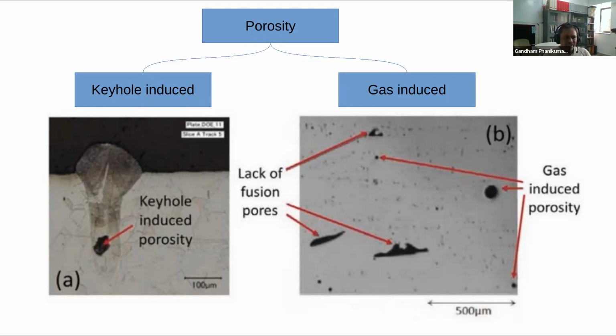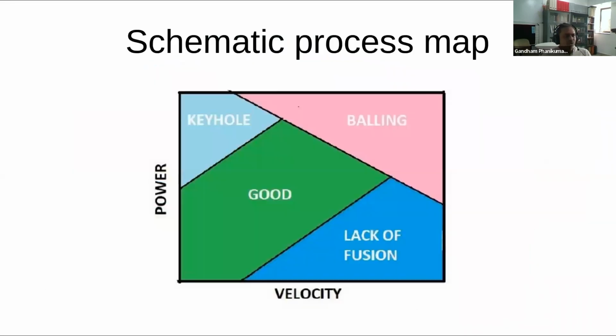The gas-induced porosity is difficult to eliminate using the powder characteristic, laser characteristics, because it is actually coming with a contribution from the powder consumable. So it's a consumable problem basically. So as you can see that there is a way by which we can understand defect formation in the additive manufacturing.